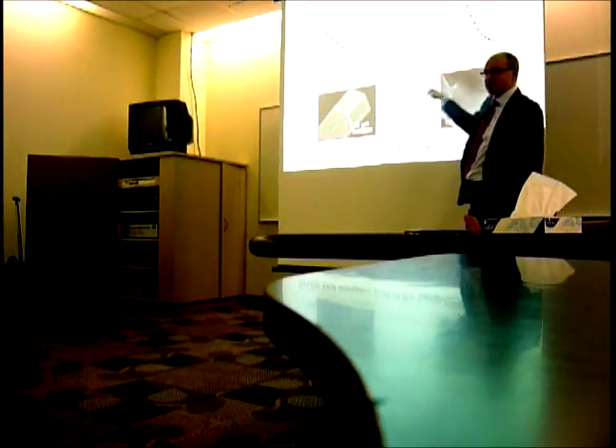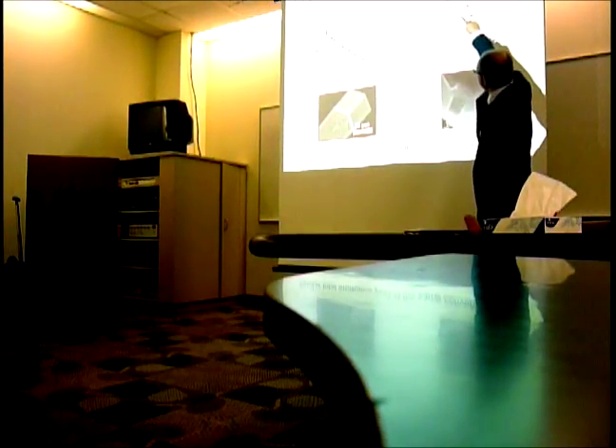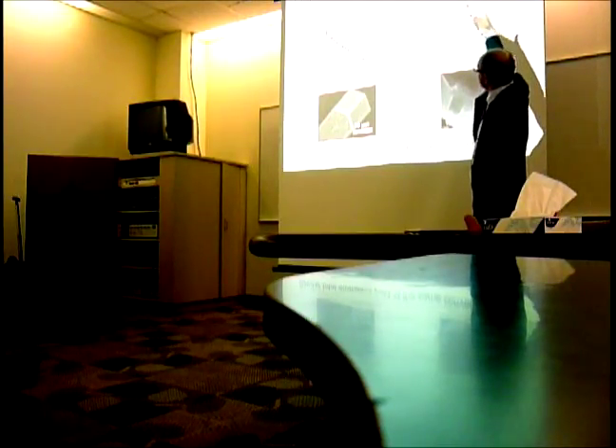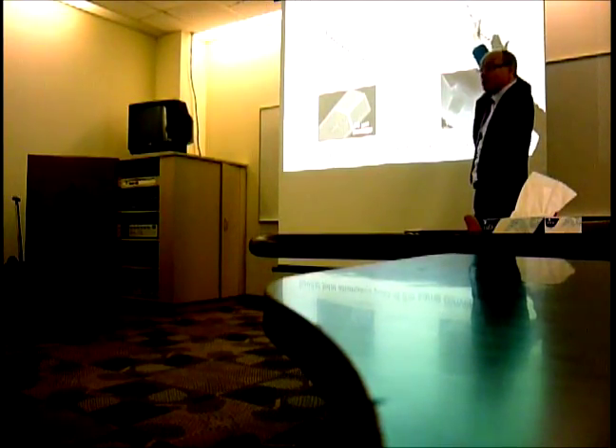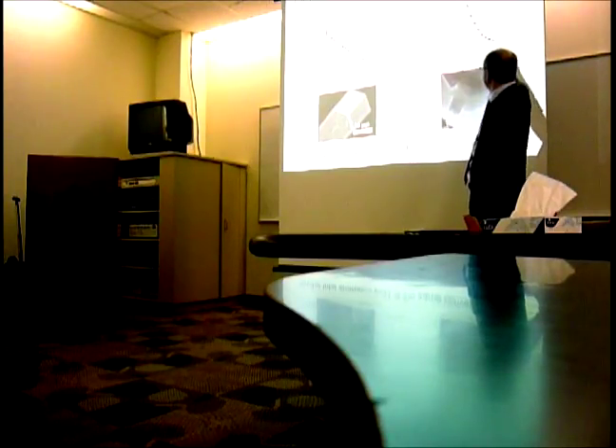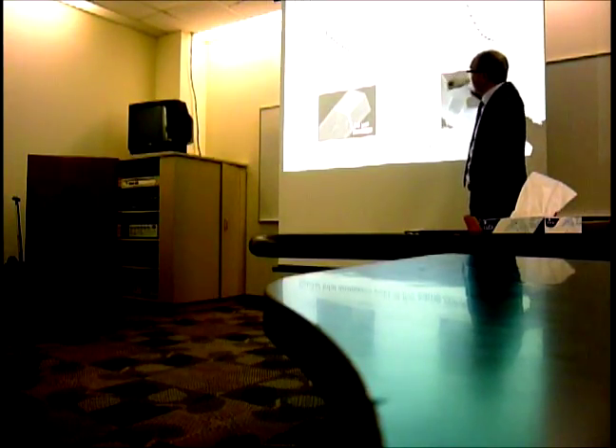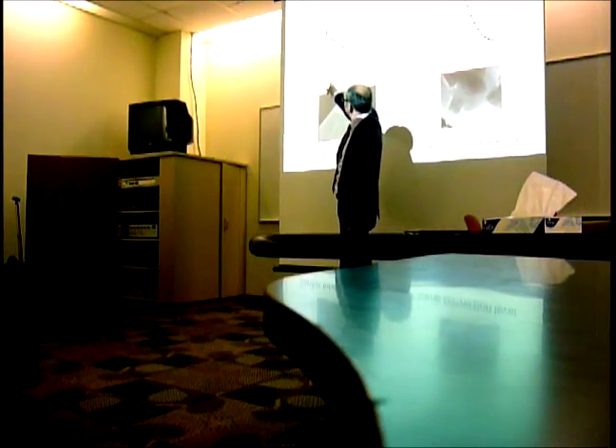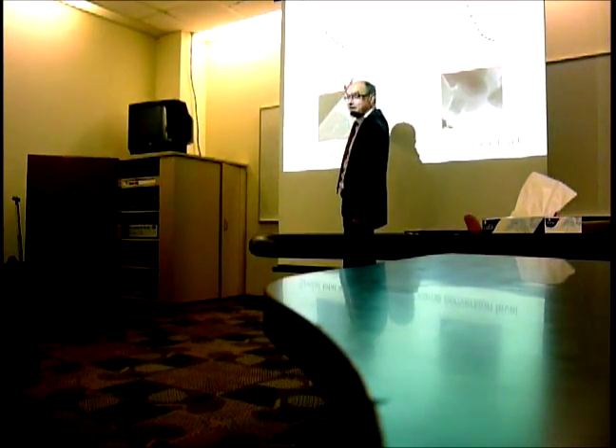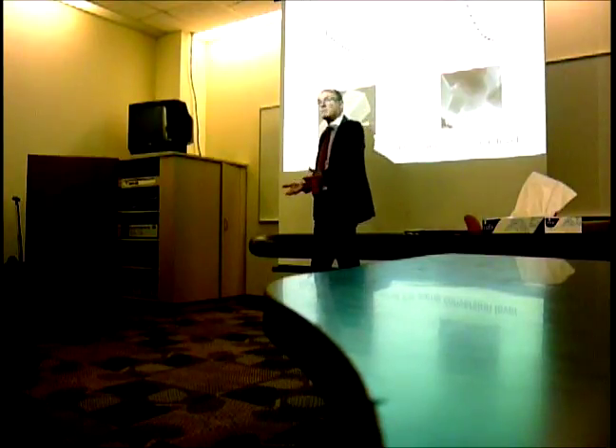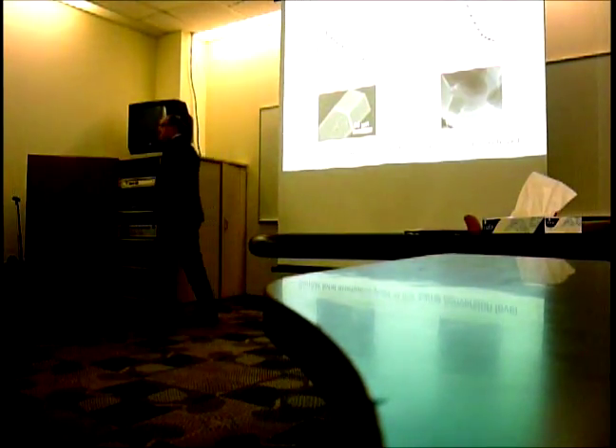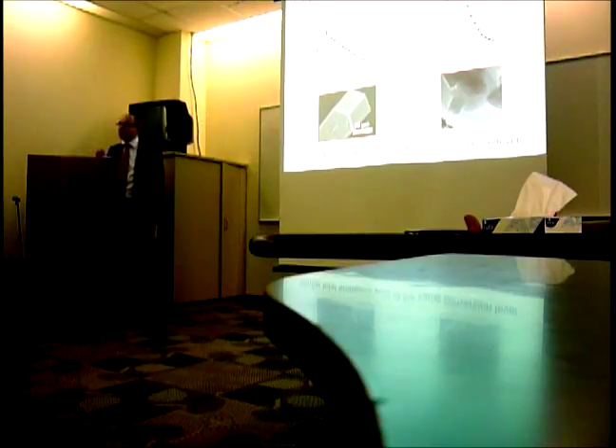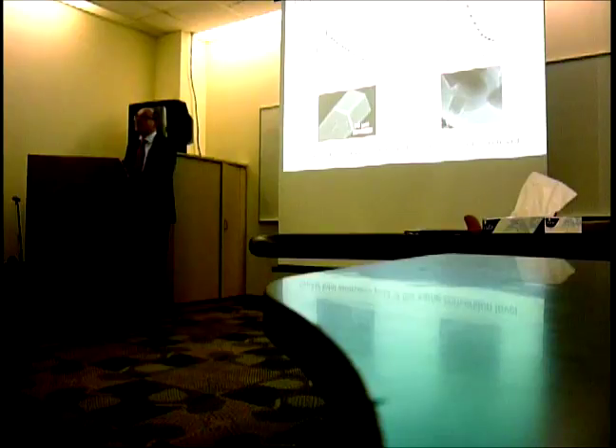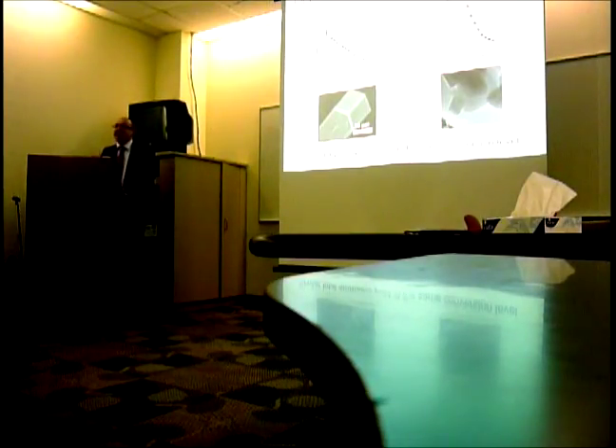So these are large crystals, small crystals. Now you see that the small crystals, the industrial sample, have a very high activity in the beginning, but steeply drop within a rather short time. Now, with these large crystals, you see time on stream, very long time, they are less active, but you can pursue for a while. So that means they are ideally suited, which somehow answers one of the questions yesterday, what the purpose can be of these model systems. It ideally suits them to do this kind of approach.